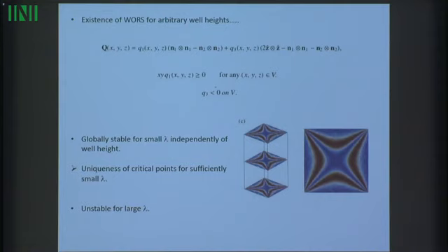The claim is that this solution is special because it has a constant set of eigenvectors. It has this very distinct diagonal defect cross. It's invariant in the z direction, and of course it has only 2 degrees of freedom, and it's negative Q3 everywhere in the domain. So it is relevant in a 3D context as well.